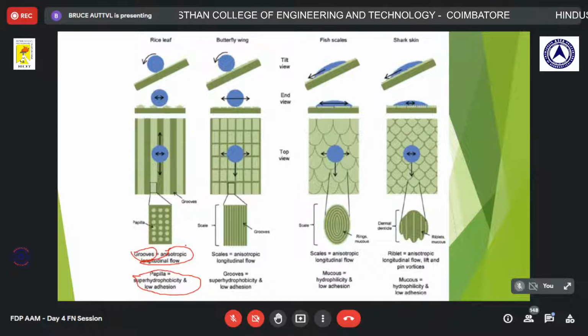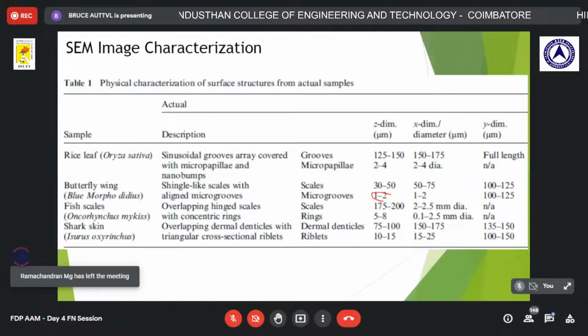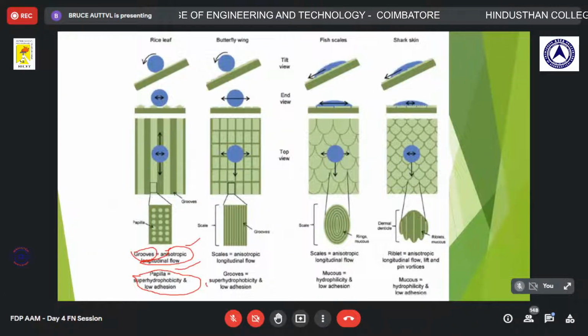And if you consider the butterfly wing, here the scales are there. The scales enable anisotropic longitudinal flow. And again, here grooves, super hydrophobicity, and low adhesion, because in the butterfly wing, the dimension of the grooves is very small. You can observe micro grooves. Here it is 1 to 2 micrometers. Okay, so these micro grooves enable super hydrophobicity and low adhesion. And it is particularly in the case of a moisture environment. If you perform some experimental analysis in the moisture environment,